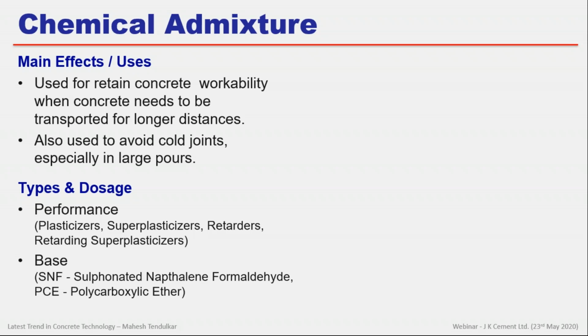So initial slump will be increased, so we can transport the concrete, place the concrete, and compact the concrete. And if it is a big pour, we don't want a cold joint, so we want to delay the setting time. That is called a retarder or retardation. But nowadays, these admixture companies have done very good study, and they have come up with an admixture which has both effects. They call it a superplasticizer or retarding superplasticizer. So depending on the requirement, they have the retarder dosage inbuilt in a one-pack system. Ideally, we can add two separate systems, but now we can have a one-pack system which is a retarding superplasticizer.